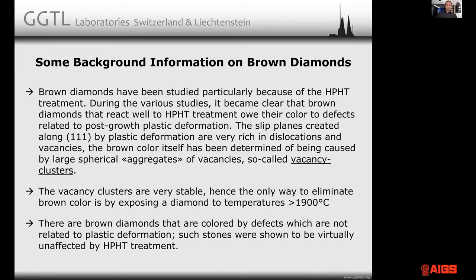Now, there are some brown diamonds that are colored by defects which are not related to plastic deformation. Such stones, in contrast to the stones that react to HPHT treatment, barely do anything with standard HPHT treatment unless you go to extremely high temperatures where you start modifying the nitrogen aggregation state. But since they don't have plastic deformation-related defects, they don't react to a treatment at about 2,000, 2,100 degrees.